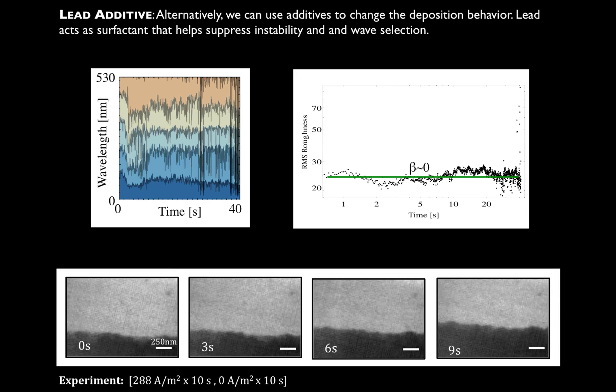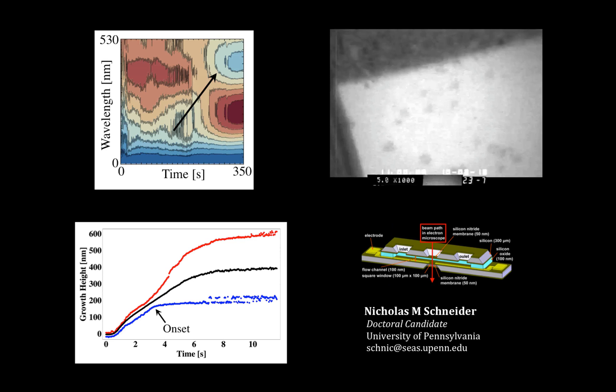If we look at the autocorrelation wavelengths, as a function of time it didn't change — we still see all those wavelengths existing throughout the experiment, meaning we're not having wave selection. With that, we've developed a way of quantitatively looking at our surface growth and morphology changes. We use measures of the max/min height, the average height, the RMS roughness, and the extracted wavelengths via autocorrelations to understand what happens when we use active and passive controls, and also to understand basic copper electro deposition. I'd like to take any questions.